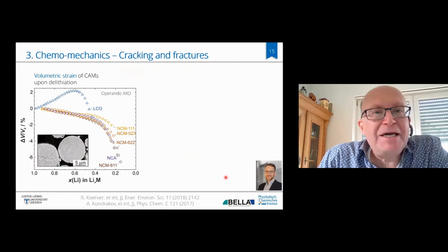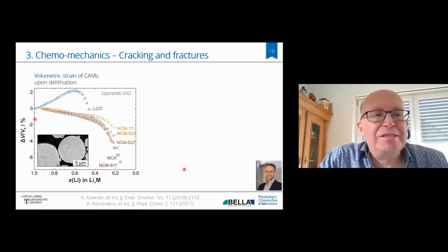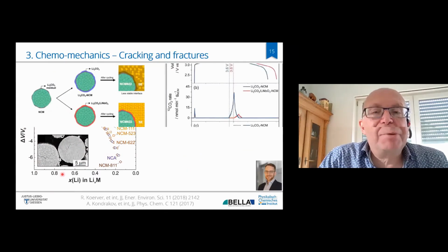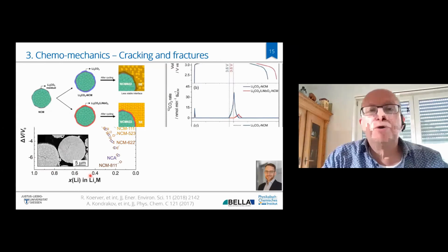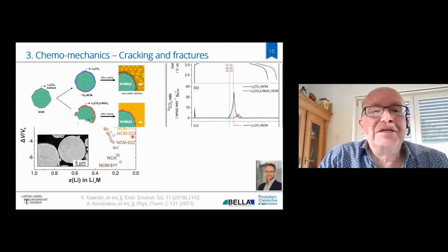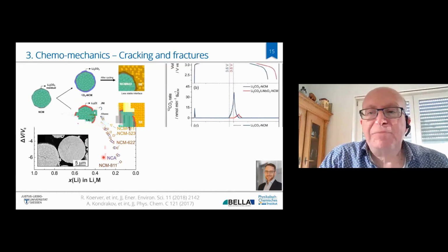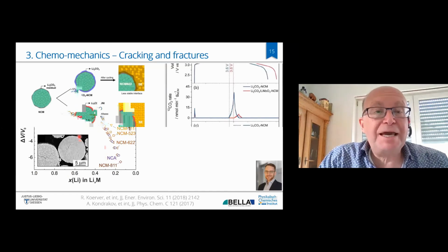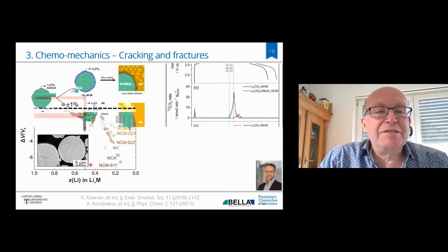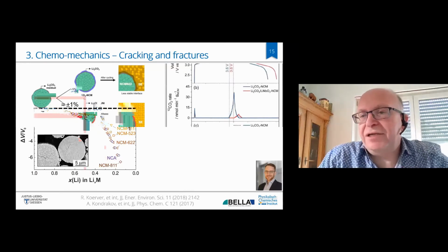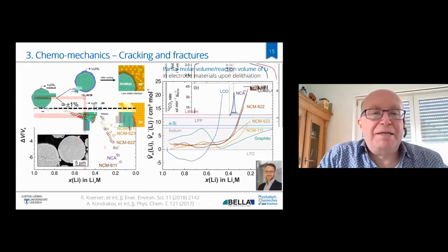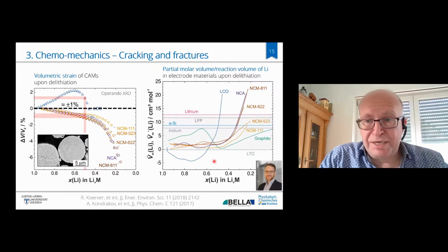Now let me come to chemomechanics. What you see here is the volume change of cathode active materials. So lithium cobalt oxide is expanding upon delithiation, because you remove the Coulomb glue between the oxide layers. Well, all the nickel containing materials, NCM, NCA, NCM 811 and so on, they all shrink during delithiation because nickel is being oxidized to the small nickel 4+ ion. That overcompensates the Coulomb effects between the gallery. The effect, however, is not too big until half delithiation. It's only 1%. But if you calculate the volume change, it's enough that particles may lose contact and that they crack. This is, of course, well known.